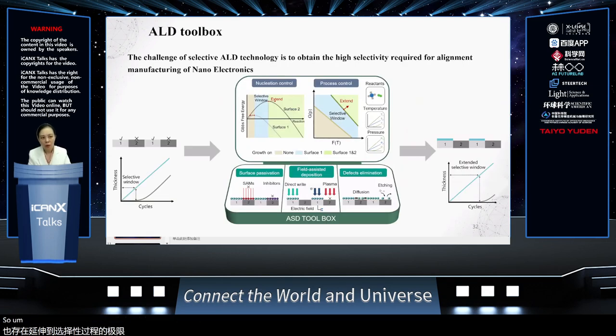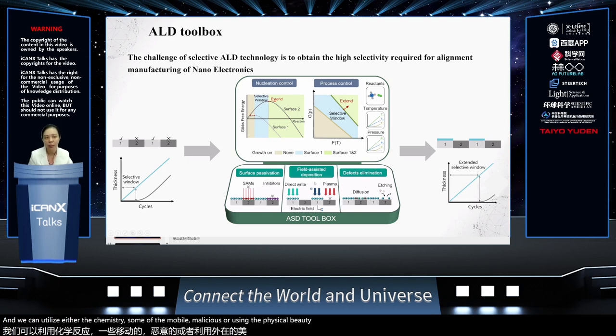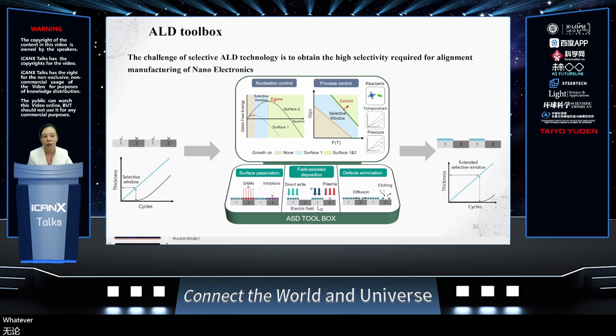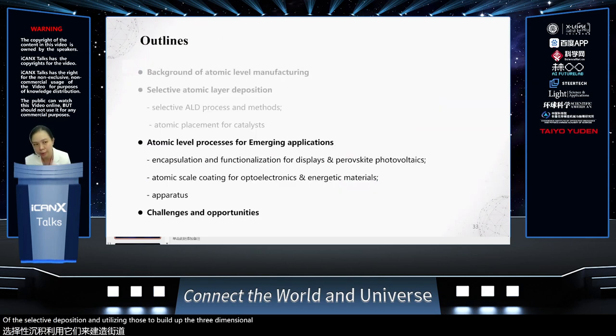So with all of that, we have the parameters of temperature and pressure, and we can utilize either chemistry, surface monolayers, or physical field assistance like plasma. We can also add a layer of etching or removal step to remove the extra material. For all of this, we can pick whatever we want to obtain very good control of the selective deposition and utilize that to build up three-dimensional structures. And then next, I'm going to talk about the atomic level processes for emerging applications.